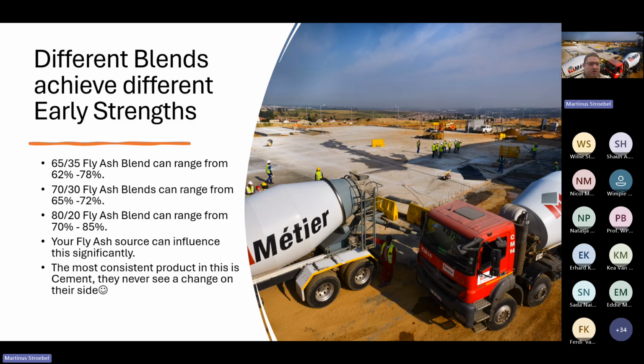And all the history and all the literature shows that the durability is not compromised with fly ash. It actually increases your durability. So it's still not a bad quality concrete, but it might not meet your expectation, and we have an unhappy customer, even though the concrete is of good quality. And then I have to say, there's a bit tongue-in-cheek.